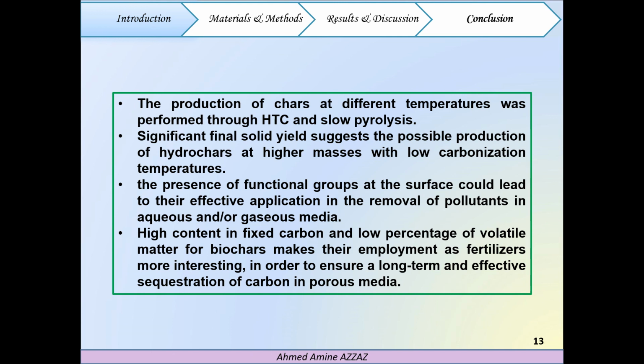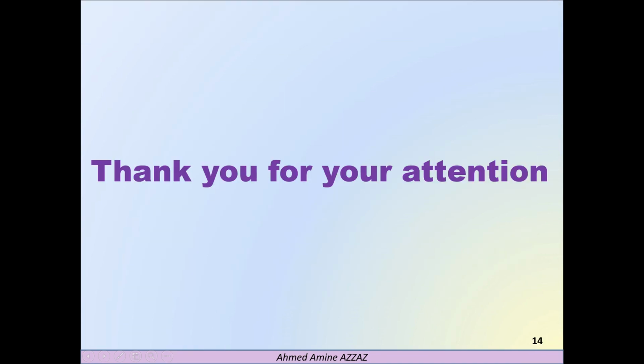So, as a conclusion, the production of chars at different temperatures was performed through hydrothermal carbonization and slow pyrolysis. Significant final solid yield suggests the possible production of hydrochars at higher masses with low carbonization temperatures. The presence of functional groups at the surface could lead to their effective application in the removal of pollutants in aqueous and or gaseous media, and high content in fixed carbon and low percentage of volatile matter for biochars makes their employment as fertilizers more interesting in order to ensure a long-term and effective sequestration of carbon in porous media. And at the end, I would like to thank you for your attention.